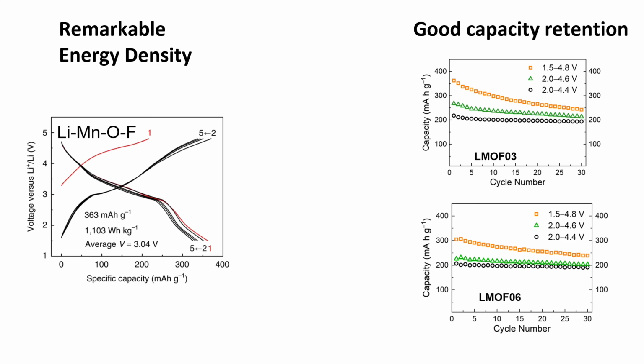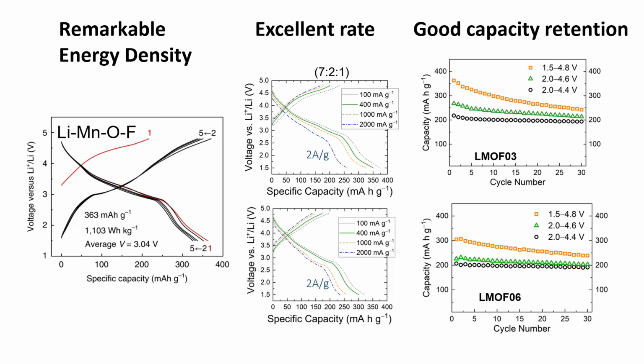And these materials work remarkably well. They are probably today the best performing intercalation cathodes we have ever seen. This material achieves about 1100 watt-hours per kilogram. To put that in contrast, a typical NMC is about 700 or 750. Does it with very good cycling, but maybe remarkable, does it with amazing rate capability. So here's a discharge at 2 amps per gram. Again, typically we look at things that do like 20 or 100 milliamps per gram. So this material not only has amazing energy density, but also has amazing rate capability. And by the way, it only uses manganese, right? One of our cheaper transition metals.